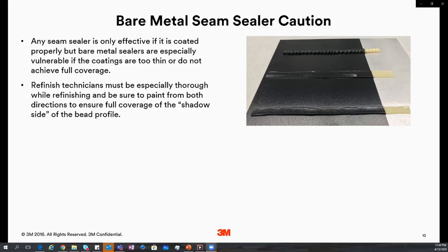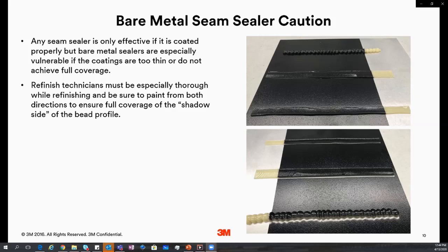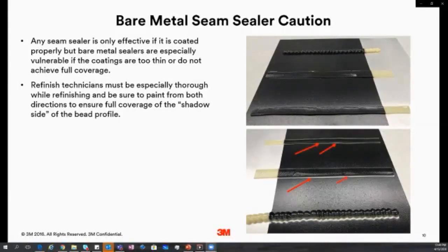Communication is going to be key here outside of just the application of the product, because when it's not applied properly, areas tend to get missed. And this isn't necessarily just from lack of caring. Sometimes you can't get the paint gun on the other side. And so what we end up seeing is what we call this shadow edge, where we don't have adequate coverage of a material. And if that edge is a bare metal edge, or that seam sealer is a bare metal seam sealer, and now we've got a bare metal exposed edge along that sealer, that corrosion can start there.